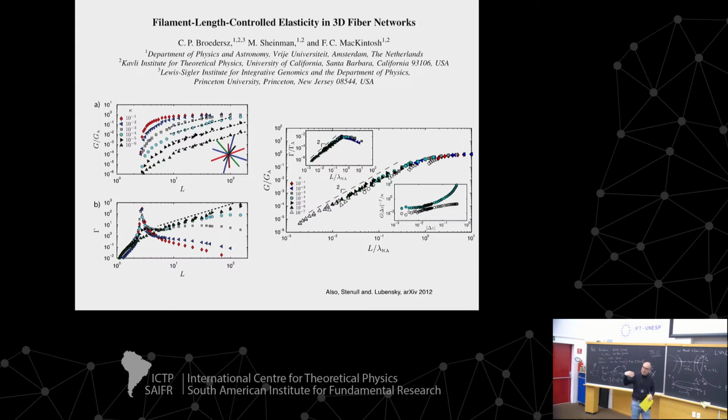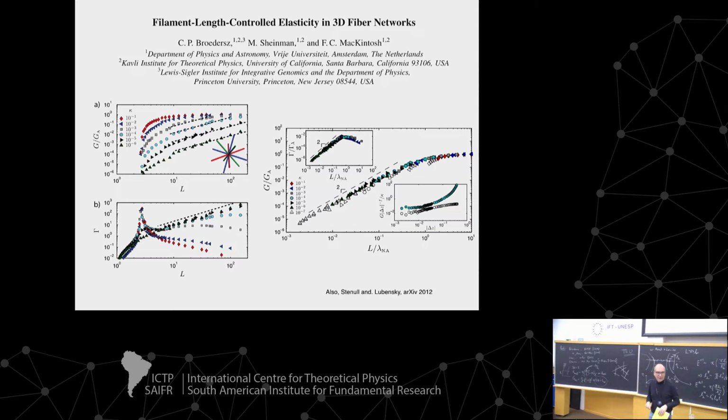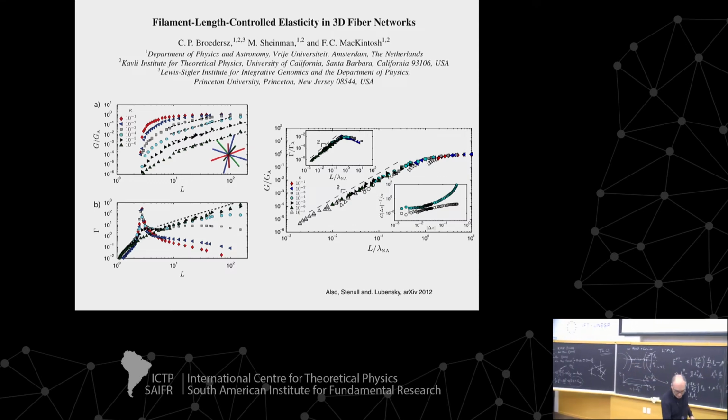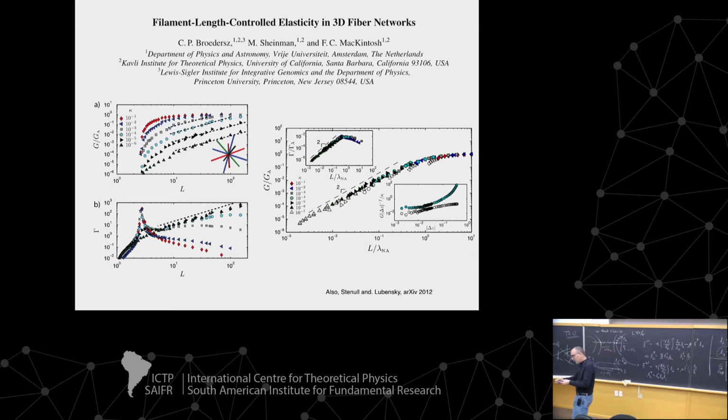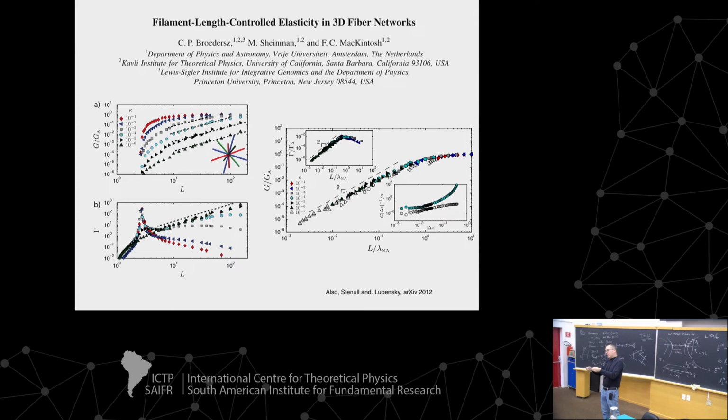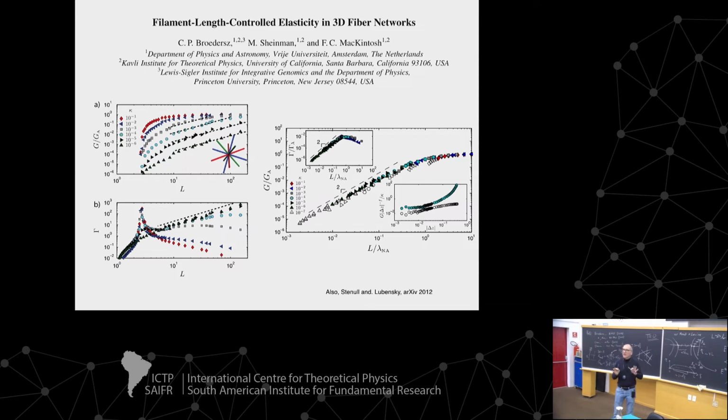It, I think, addresses your question. I should actually point out why 2D and 3D are so different in another way. So look, when two fibers cross, and if I were to pin them together, as we do in our systems, again, as I've said, I can't bend this one without compressing this one, right? Because they're so interconnected. But notice in 3D, there's no problem. Because once I put these two fibers together, they form a plane, and there's a soft mode in the other direction. So that's another reason why 3D is very different.